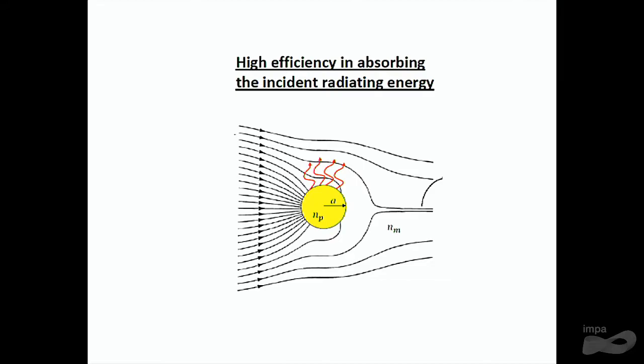So it captures light, and that light that it captures is going to be absorbed by the particle and transformed into heat. So that makes the gold nanoparticles very efficient. The efficiency is related to the material. It's not only gold, it may also be silver and platinum, those called the noble metals. And it's not only the material. If you put a big particle there, it's not going to have this reaction. So it has to be very small, in the order of nanometers.